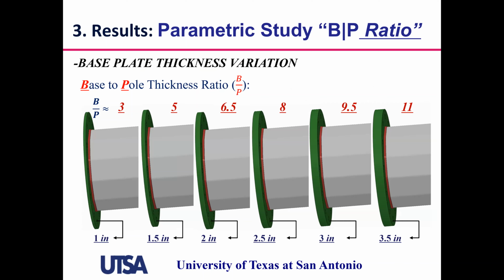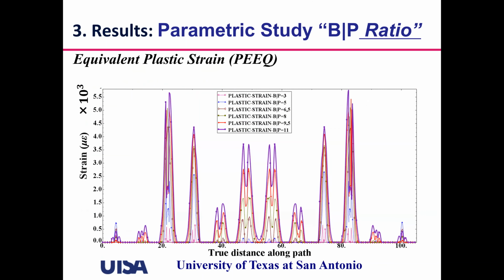Then we did a parametric study to see what would be the effects of geometry on this crack formation phenomena. So we first kept the pole thickness constant, and we changed the base plate thickness. So you see here that we considered different base thicknesses. That will give you different B/P ratios, as we call them. And here you can see the effect of the B/P ratios.